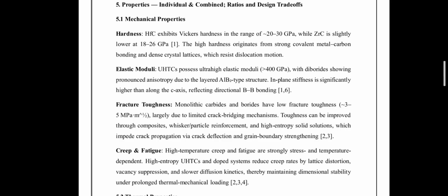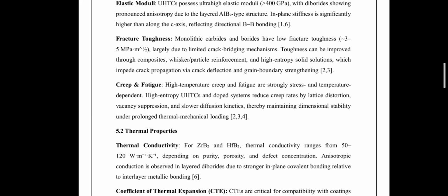Next is creep and fatigue at high temperature. High temperature creep and fatigue are strongly stress and temperature dependent, governed primarily by diffusion controlled mechanisms. High entropy doped ultra high temperature ceramics show reduced creep rate due to lattice distortion, vacancy suppression, and slower atomic diffusion. As a result, these systems maintain dimensional stability under prolonged thermomechanical loading, which is critical for hypersonic and re-entry environments.